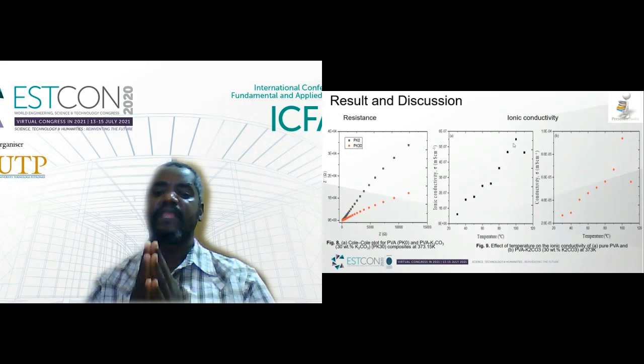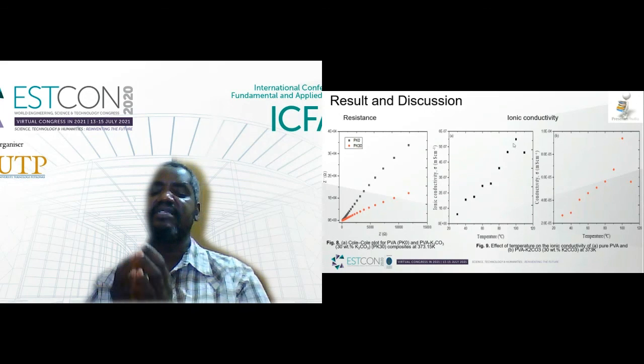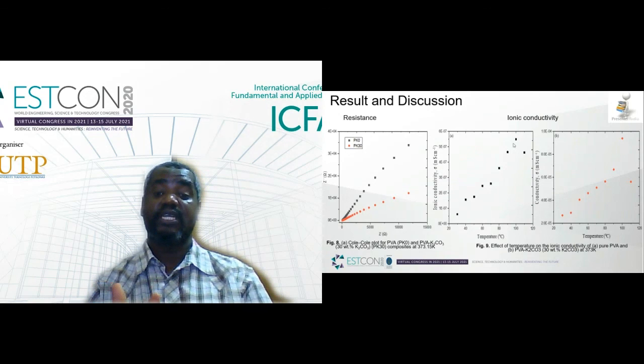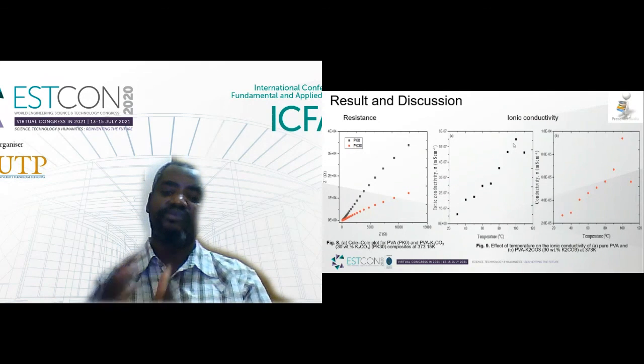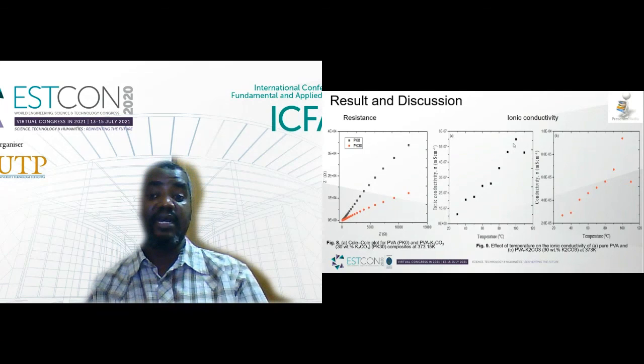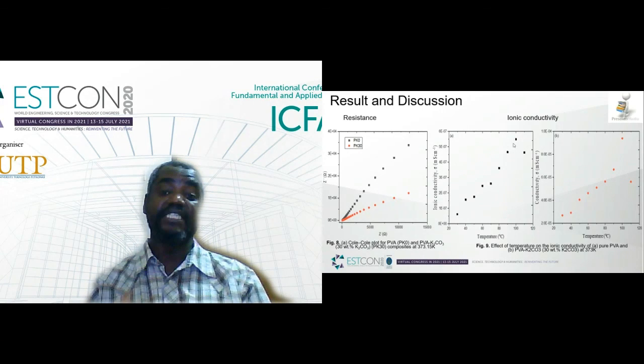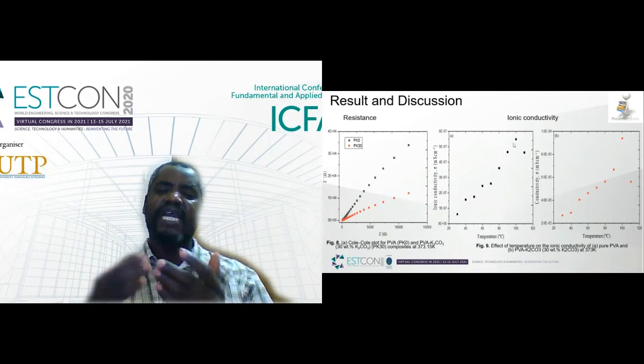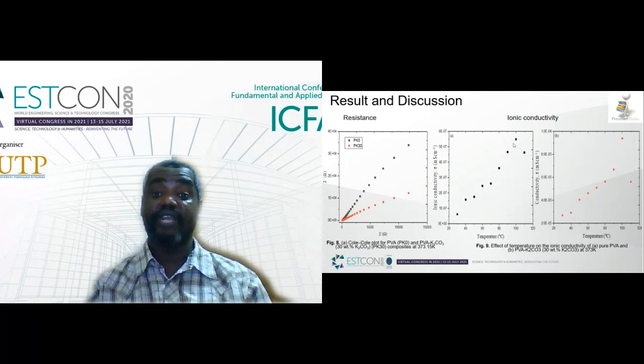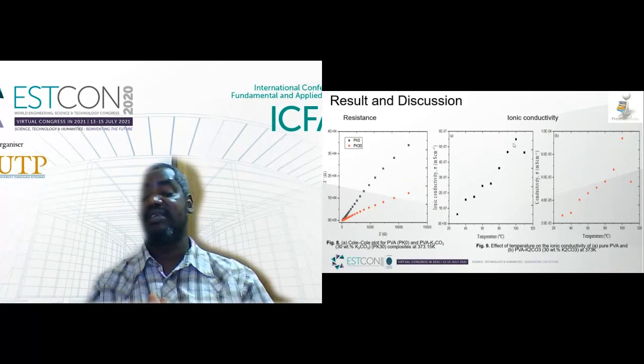This may be due to the possibility, at higher temperature, of the ion from the potassium carbonate, K+, which is an active ion, being converted into the inactive K0. Also, at higher temperature, there is a possibility of agglomeration and crystallization of ions, which also may lead to the decrease in ionic conductivity.